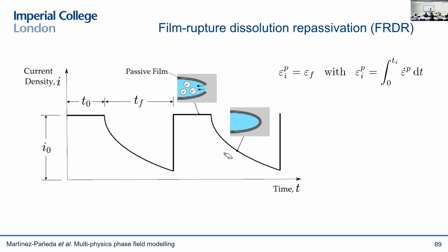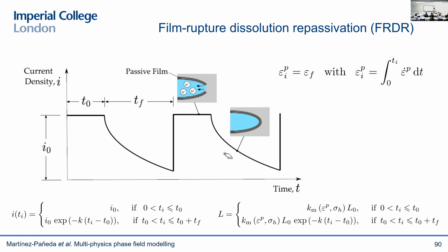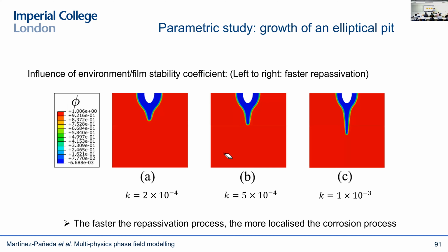So you have a situation where your corrosion current density is very high because your metal is unprotected. But then as you start passivating, you start forming the layer, you bring down the corrosion current density until your strains are large enough and you rupture your passivation film and you're back again. So we can incorporate this easily again through this mobility coefficient, and therefore we can capture the effect of changing the passivation kinetics, the material itself, and we can capture this kind of, I would say, pit to crack transition that people have been trying to predict for a long time.